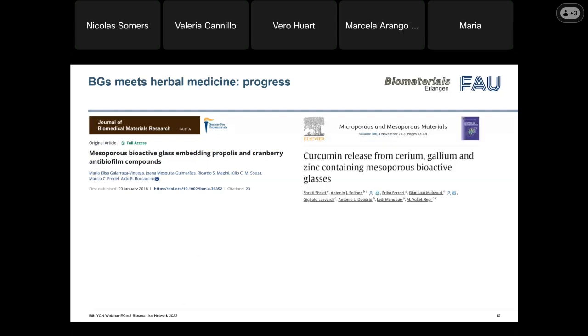Then another group studied the incorporation of curcumin, also in mesoporous bioactive glasses, and here they also produced glasses with different ions. So they wanted to see the effect of adding curcumin in glasses with different ions, or at least to see if there was a difference or if they had the same effect. And indeed, they found that, for example, when they added zinc in the composition of the glass, the loading efficiency was not as good anymore as with the other ions. They also worked on the release of the curcumin from these particles.